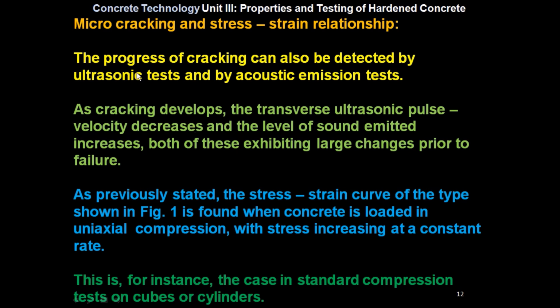The progress of cracking can also be detected by ultrasonic test and by acoustic emission test. As cracking develops, the transverse ultrasonic pulse velocity decreases and the level of sound emitted increases, both of these exhibiting large changes prior to failure.